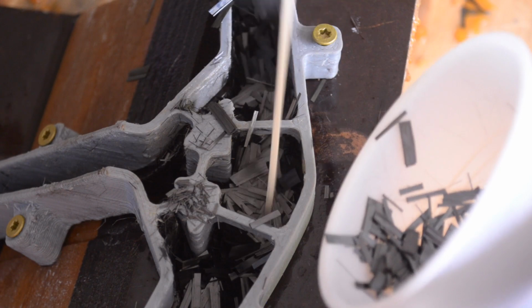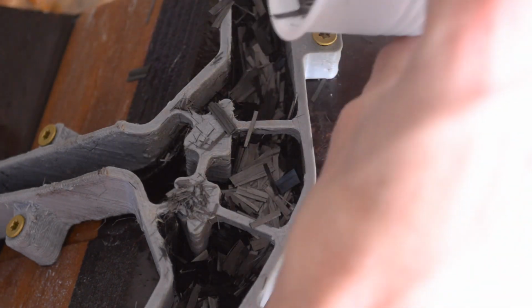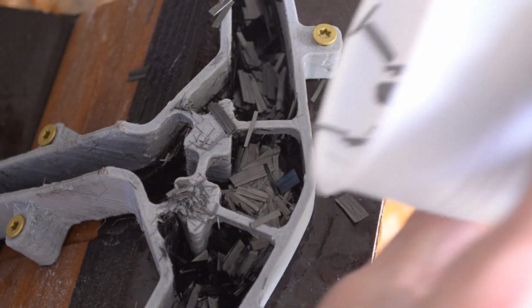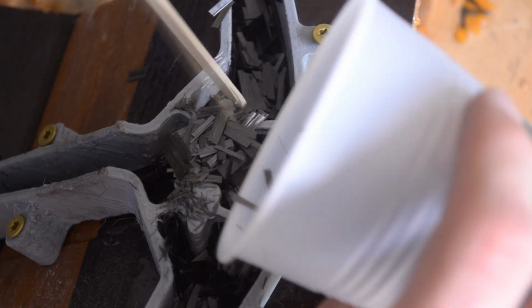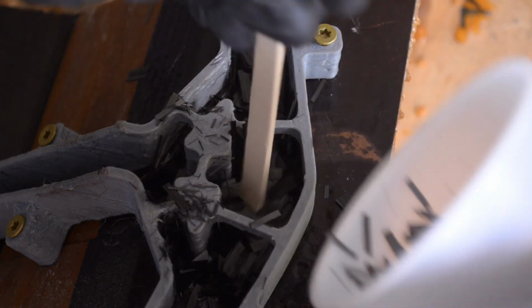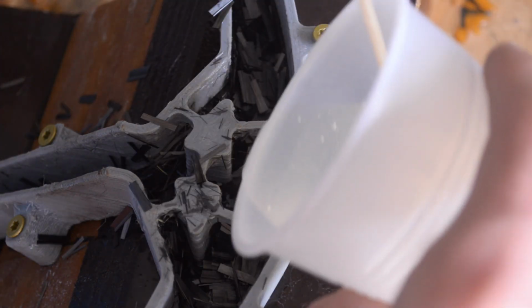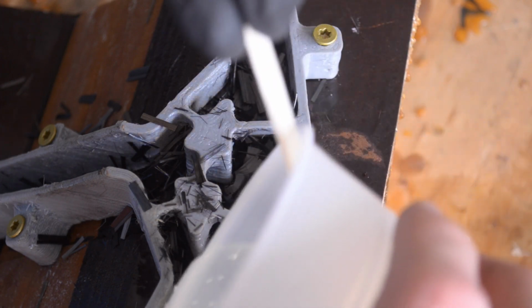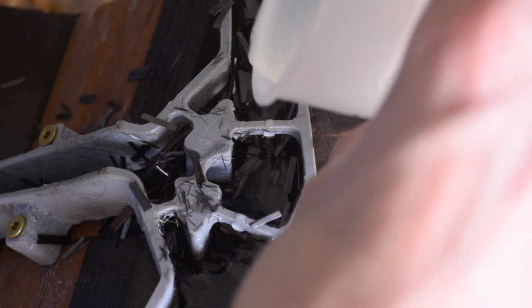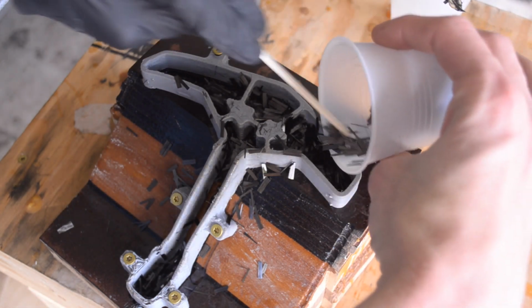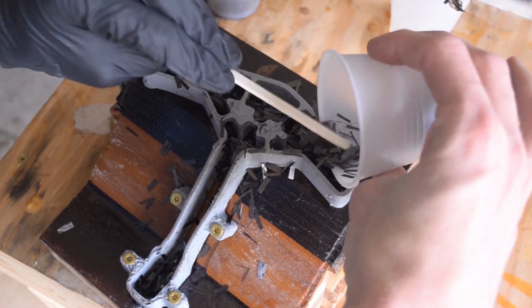And now I can put the carbon fiber in, and I have to alternate between epoxy and carbon fiber. And the carbon fiber has to go in dry, because if I put it in wet, like let's say I mix the epoxy and the carbon fiber together, it just turns into this big blob of carbon, and I don't get the surface finish appearance that I like. So that was a tough lesson to learn.